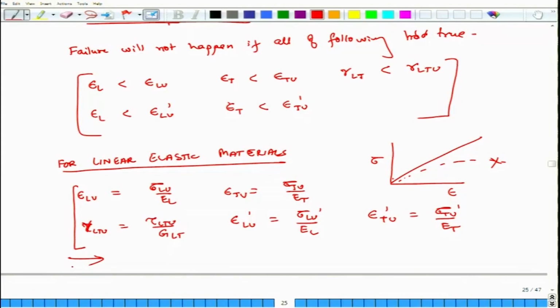But if the material is not linearly elastic, for instance the matrix is plastic and it just deforms heavily before failing, or if the fibers are initially elastic but later turn plastic before failing, then the material will not be linearly elastic. In that case, we cannot use these types of relations. We can still use the first set of relations, but the second set of relations cannot be used. So, for linear elastic materials, the predictions from maximum stress theory and maximum strain theory come pretty close to each other.